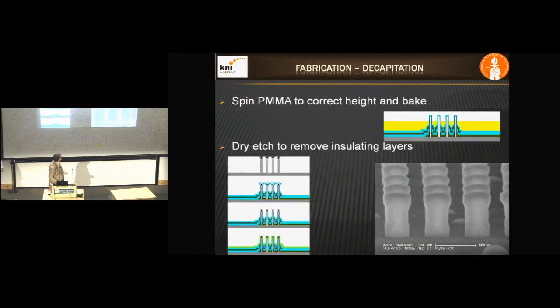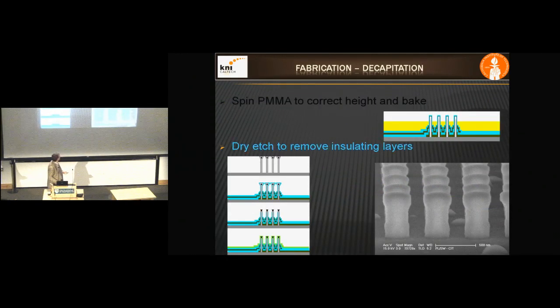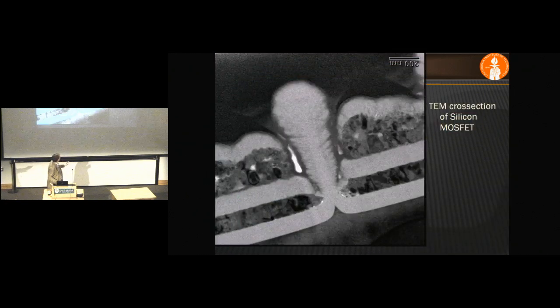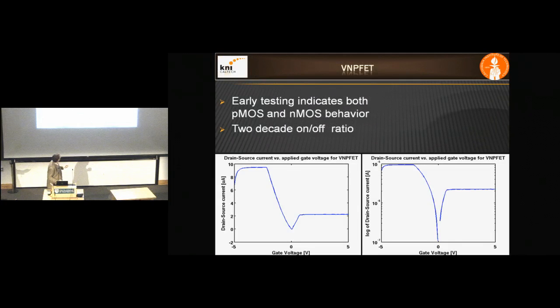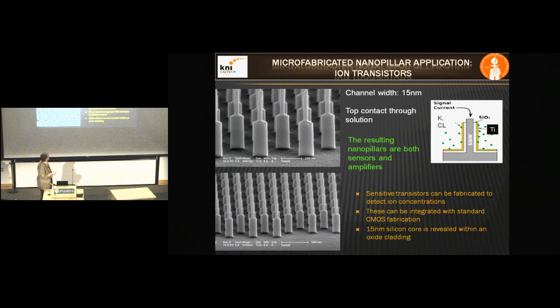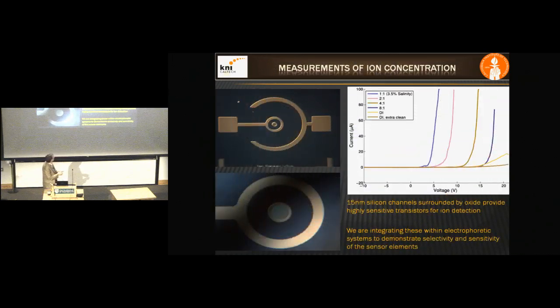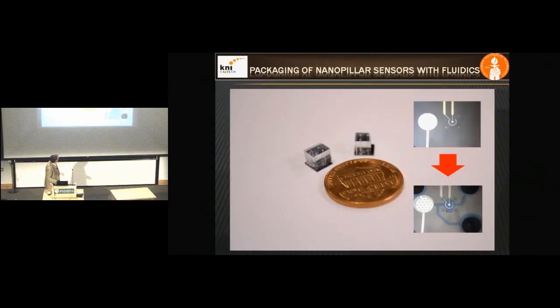Okay, and when we build those structures, it's tough to build them, but when they work, this is how they would look like. This is a TEM cross-section of one of the MOSFETs, and this is how they work. So we can make actually reasonably good transistors by making these 2 and 3 gated structures. We can also make sensors. We can make ion sensors, where this kind of gate can then absorb whatever ions are surrounding it. And you can measure the concentration by looking at the voltage at which the channel turns on. So it's a nice little ion sensor. The dimensions are 15 nanometers for these. You can package them. This is what they look like when they're packaged.